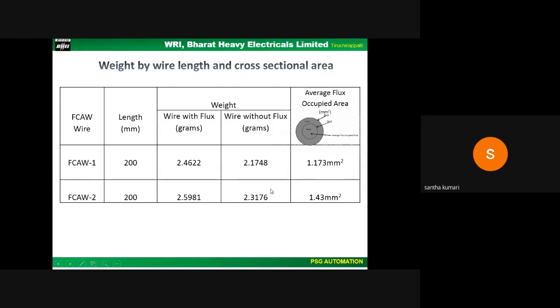Here we tried two different fluxes, the same flux from two different suppliers. We tried to evaluate this flux core wire by the conventional method of wire length and cross-sectional area. We can see here the average flux occupied area of the second sample was higher than that of the first one.